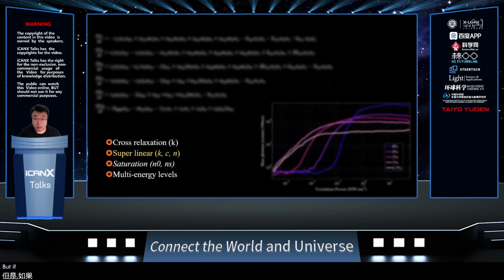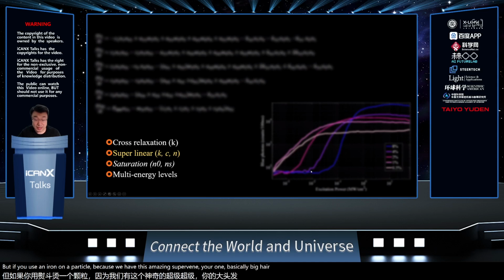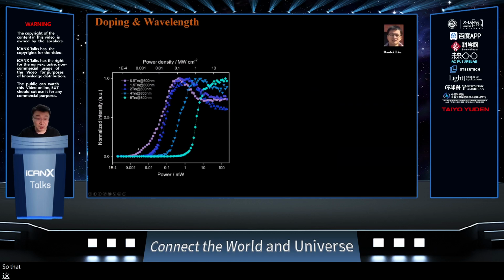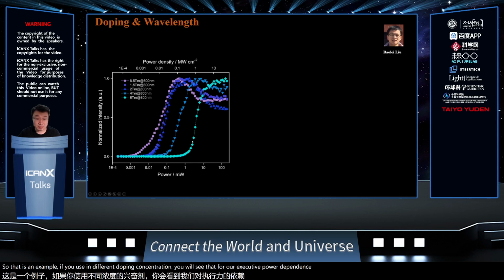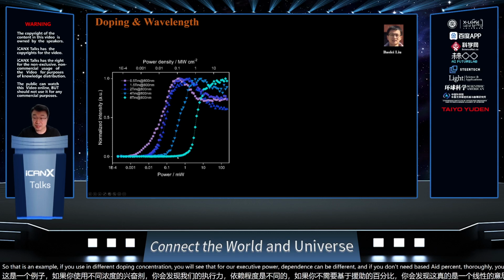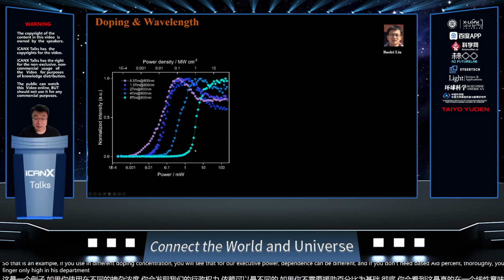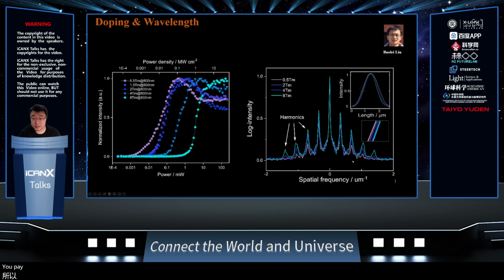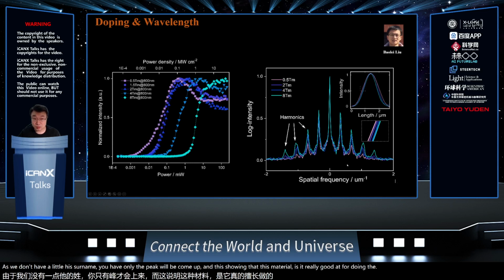But if you use our nanoparticles, because we have this amazing superlinear response, we can take advantage of it to design a low-power, nonlinear SIM. So that is the example. If we use different doping concentrations, you will see that our power dependence can be different. If you dope with 8% thulium, you will see that it's really, really nonlinear, meaning that if you use some fringe pattern, only the high-intensity part will have emission. If you plot this in the frequency domain, you will see that as we heavily dope with thulium, your harmonic peaks become higher. This shows that this material is really good for doing nonlinear imaging.